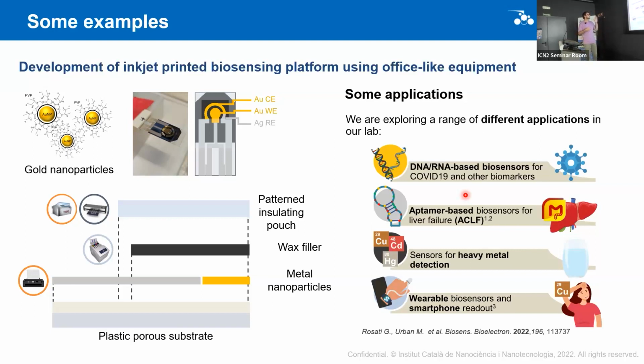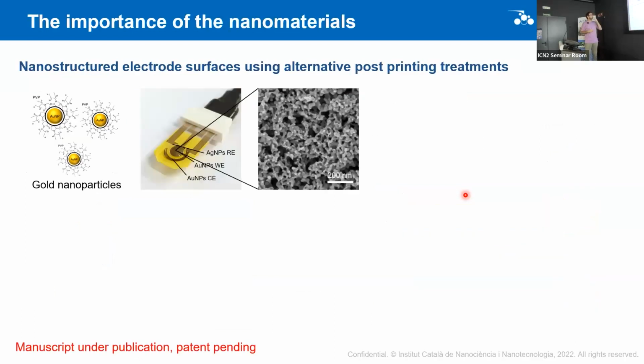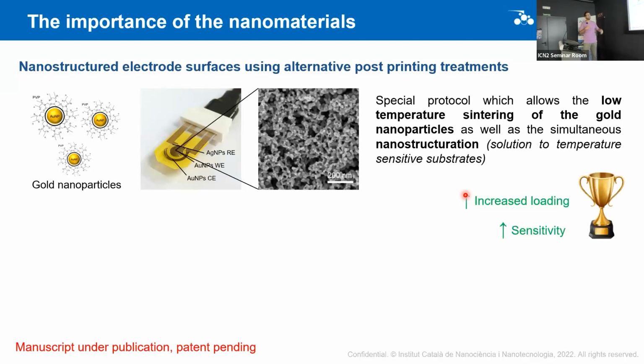In particular, these gold nanoparticle electrodes, as I was saying, are printed on a temperature-sensitive substrate. So it was a problem, because there is a procedure called sintering that usually requires high temperature to make conductive films of the nanoparticles. In this case, we had to find crafty ways to do it without using temperature. And we found that using a special treatment that doesn't require temperature, done chemically, we are able to sinter the film as well as nanostructure it.